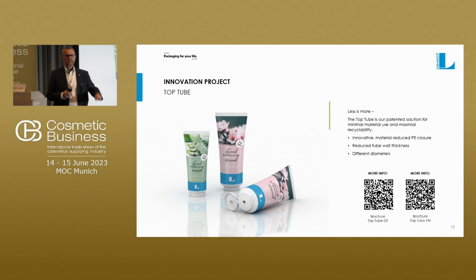So what is the result of that? It allows us to have a top with significantly reduced height and weight, and using two closure sizes, we can actually put a top on 4 different tube diameters. So we start with the 40 diameter for 40 and 50 diameter tubes, and as a second step we want a flip top for 30 and 35 diameter tubes. Why do we do that? We want a full product family, a full tube family, where you have one single lid.